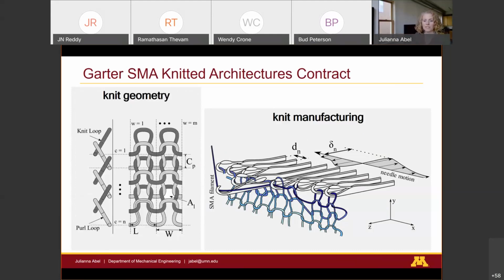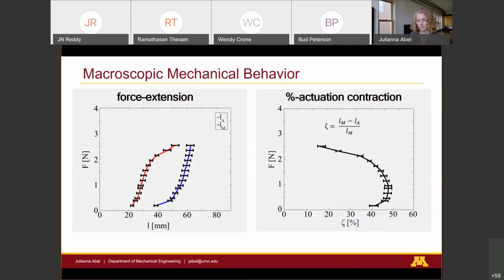And then the performance, how much it actually contracts, how much weight it pulls, is all a function of the geometry. So you have a wire diameter, you have loop sizes, you have number of loops in the course-wise or wale-wise direction. And so we can tune all those parameters to get a performance for an application. To characterize these, we conduct constant force actuation tests where we apply a weight to a sample in a cold state. We heat it up to see where it contracts to, and then we cool it back down. And we do that a couple times. We increase the applied load and cycle through.